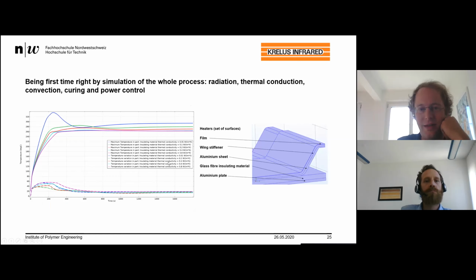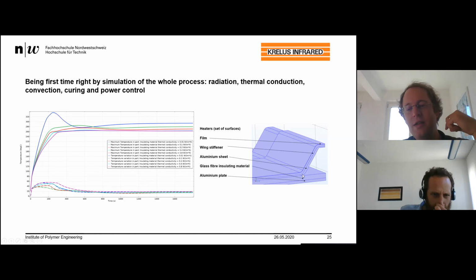Okay. Now I would like to go a little bit into detail again. As I said, we have this complex setup, and we can play around. One design factor is the glass fiber isolating material, which is below our mold. Here you can see the result of a parametric study which we performed. We changed the thermal conductivity a little bit, and related to this, we can modify the process. For instance, the blue curve shows that there's nearly no heat flow through the thickness direction.